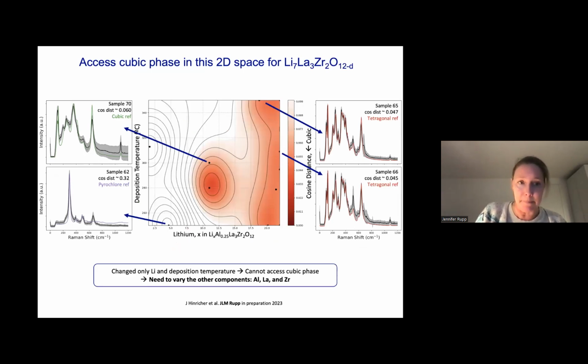And this is now one example where, for instance, we have deposition temperature that we made in sequential deposition synthesis. And we can create these maps where we can show you, for instance, this is what happens in the phase map if you just change the lithiation level. What's beautiful about it is, when you take the averaged information of the Raman spectra of many samples, about 80 samples, then we can say, well, the samples created around 300 degrees Celsius deposition temperature, with a certain post-annealing that we applied to all of the samples, then we can actually see that there are some that are very close to the cubic reference, those over here in the very highly red zones.